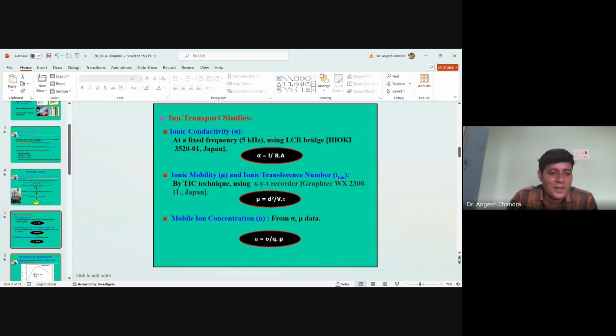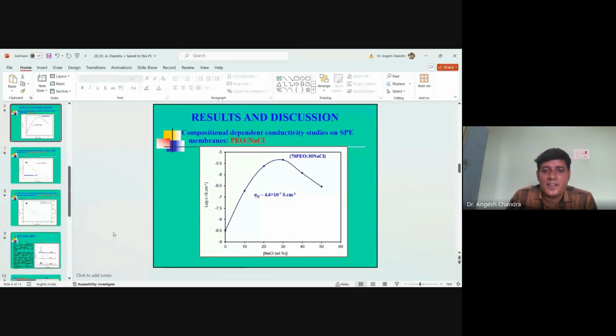Now in the results, this is the compositional dependent conductivity of PEO and NaCl. We can see here that as the concentration of sodium chloride increases, conductivity also increases, and the maximum conductivity is obtained at 30% of sodium chloride, with an ionic conductivity of 4.6 into 10 to the power minus 7 Siemens per centimeter. This has been used as a first phase host matrix for the formation of the present blended solid